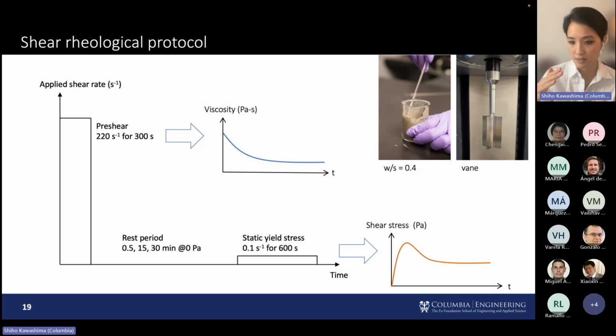So when we apply the pre-shear, we looked at the viscosity decay. When we impose the intermediate shear rate, we got this stress evolution, right? So this is kind of a typical depiction of the flow response. You have this initial elastic component, and then there's this peak, and that indicates flow onset. So there's visible deformation of the material, and that indicates your static yield stress. And then if you continue to shear your material, it eventually reaches a steady state, and that can be considered as your dynamic yield stress. So that's the minimum stress that's needed to keep your material in motion.